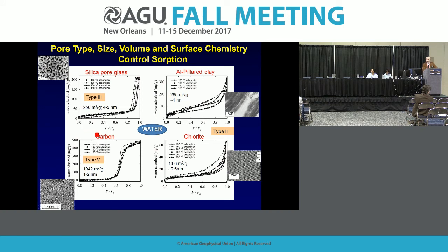You can see for the pore glass and even for the carbon, you see very little uptake early on at modest pressure until you get this rapid rise, which really indicates pore condensation. Conversely, look at the clays and the chlorite, you start building a layer, a monolayer, early on because there is a stronger attractive force between water and those charged surfaces. You see the different images here of what these things look like. So this is a macroscopic measurement, but it's giving us really microscopic information if you think about these kinds of interactions and the shape of these particular curves.